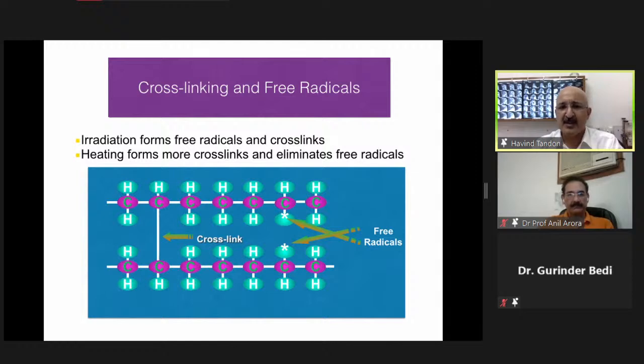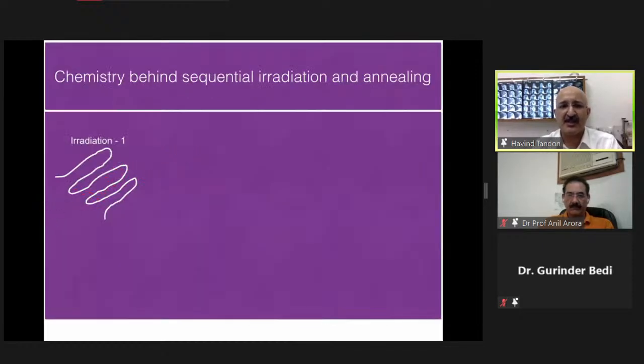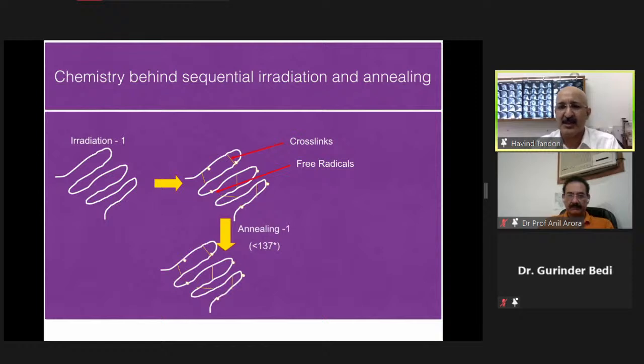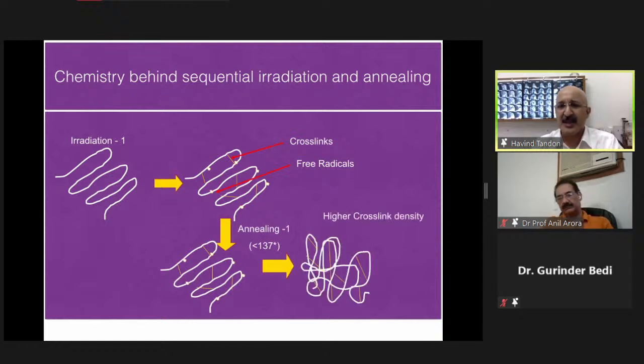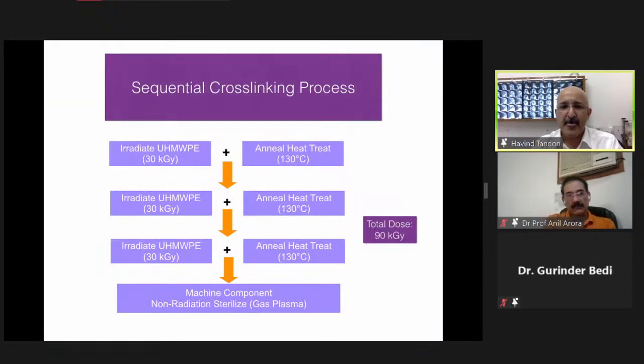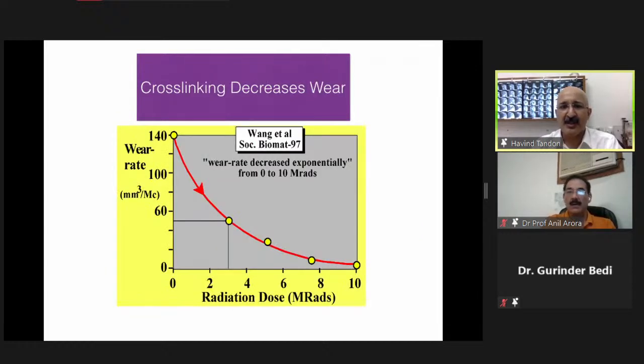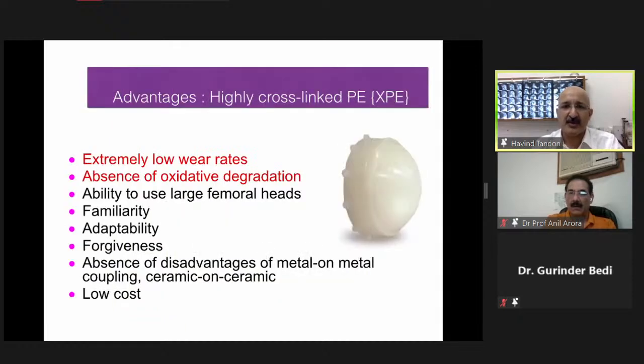For my friends, the cross-linking: we irradiate the poly, it generates free radicals also, which need to be taken away. You can see in this, once the irradiation has been done, cross-links are made, but at the same time, some free radicals get generated, which need to be annealed to a temperature less than 130, and this increases the cross link density. So this process has to be repeated many times to make it stronger. So this has shown to decrease the wear and increase the survivorship of the poly that we use.